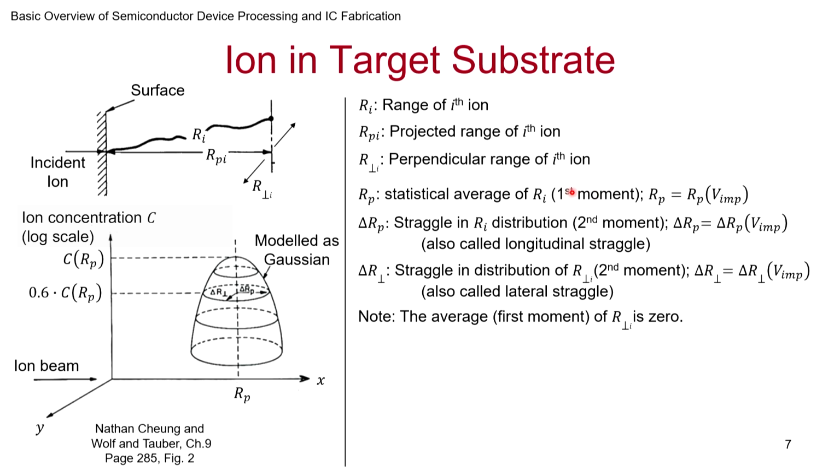And here I want to bring in a little bit of the physics of it. Note that this Rp depends on the bias that you are applying for implantation. So the energy that this ion gains will be the electronic charge times the number of charges present in the ion, usually it is 1, so electronic charge times V implantation. That is the kinetic energy with which it is crashing in, and the Rp that you get statistically would be a function of that bias of implantation that you are using.